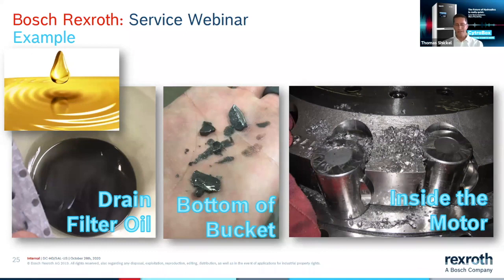So the oil was changed and a new motor was then mounted, but the oil, upon being changed, was never flushed through, and there was some remaining residual contamination left in the piping and some of the other components within the system. So upon putting on the brand new motor and again having recontaminated fluid, it was only a matter of a few minutes before the oil again began to diesel, particulate flushing through the system, and again you had another catastrophic failure.